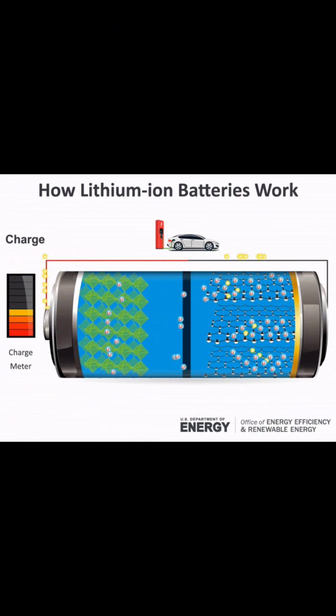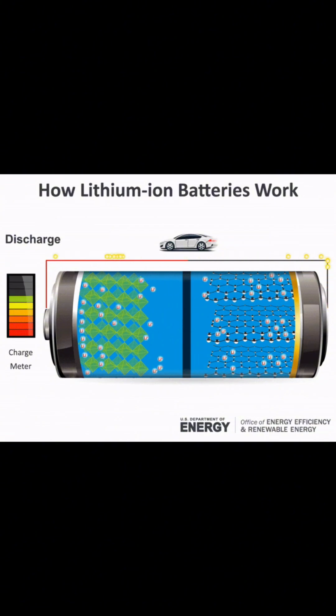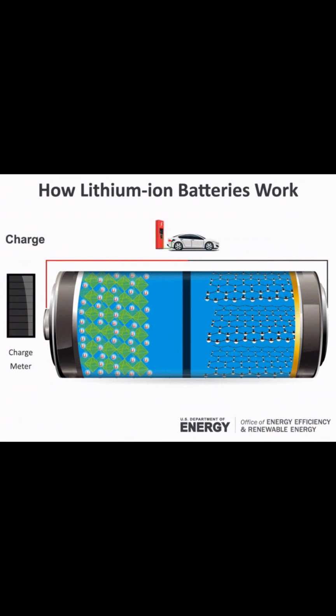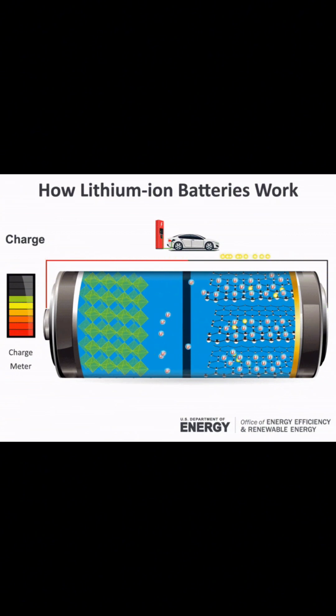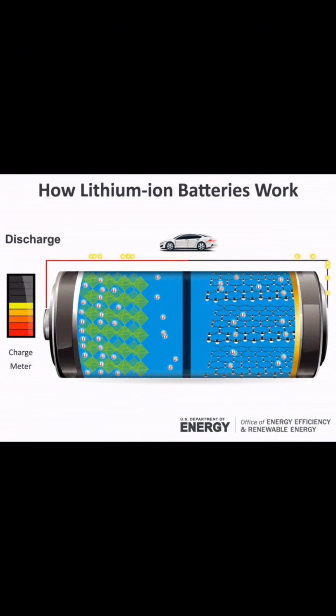In the past, lithium-ion batteries could not be fast charged and needed at least 2 hours to fully charge. Current generation cells can be fully charged in 45 minutes or less. In 2015, researchers demonstrated a small 600 mAh capacity battery charged to 68% capacity in 2 minutes and a 3000 mAh battery charged to 48% capacity in 5 minutes. The latter battery has an energy density of 620 watt-hours per liter. The device employed heteroatoms bound to graphite molecules in the anode.